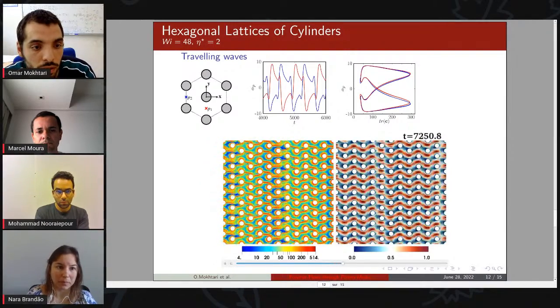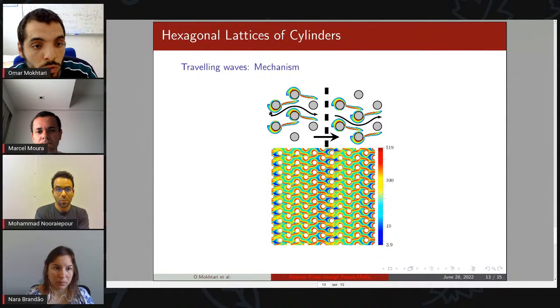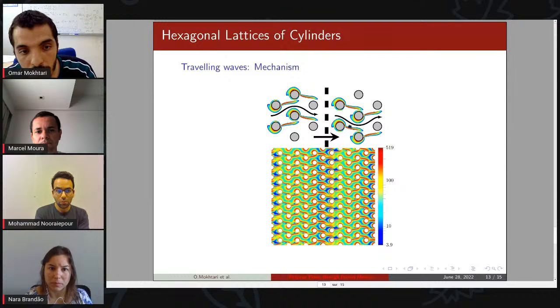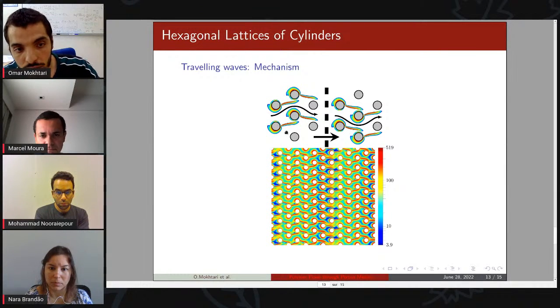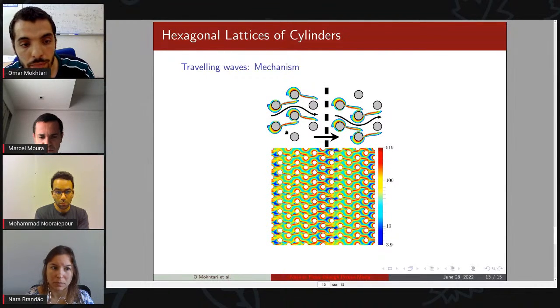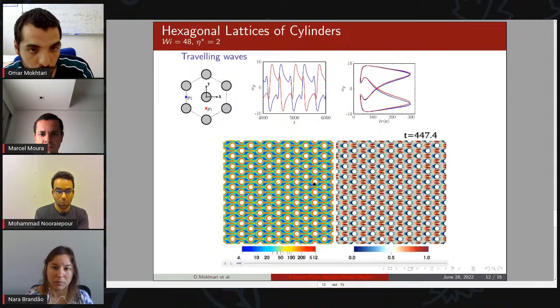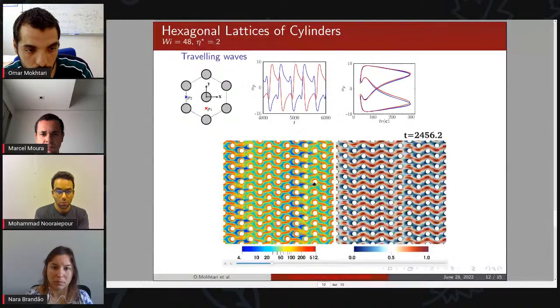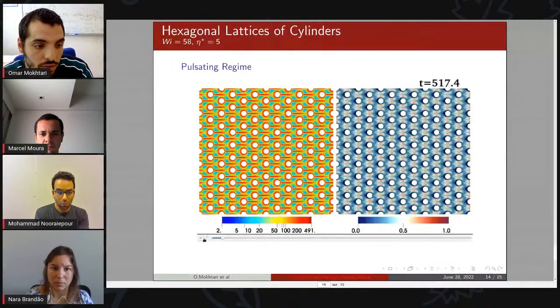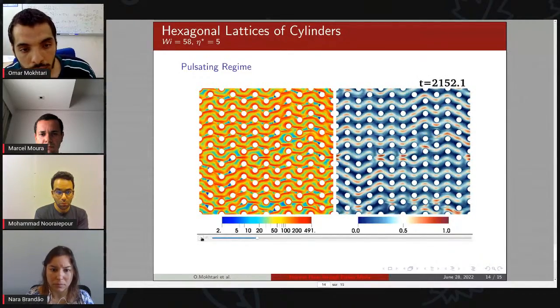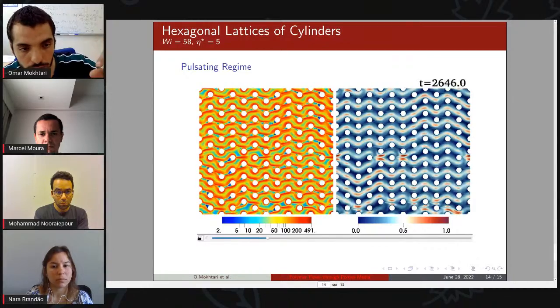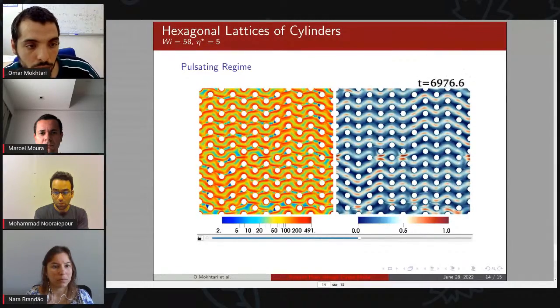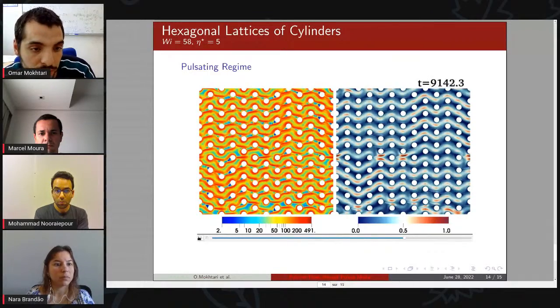To understand this mechanism, it can be understood by the two coexisting states: a state where the strands stick on the top, and a state where the strands stick on the bottom, and the wave corresponds to a switch between these two states. Okay. By further increasing the Weissenberg number, we observe a very complex pattern of the strands, and this pattern is now fixed with small oscillations. This corresponds to a pulsating regime, with small oscillations around a preferred fixed pattern.